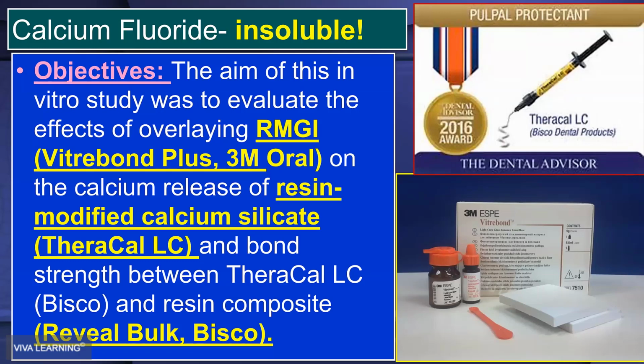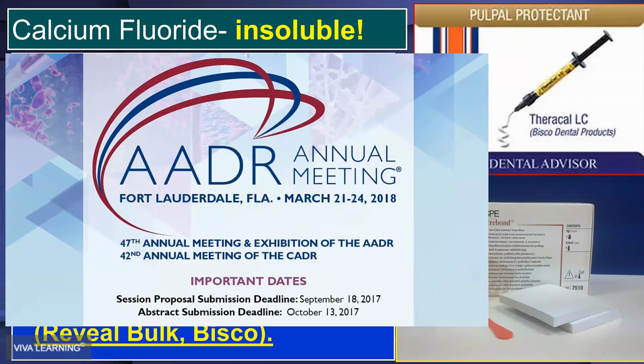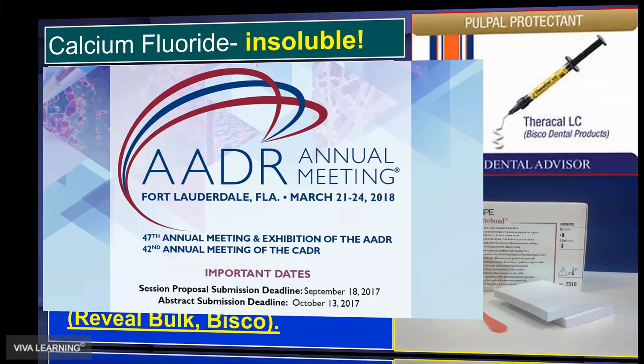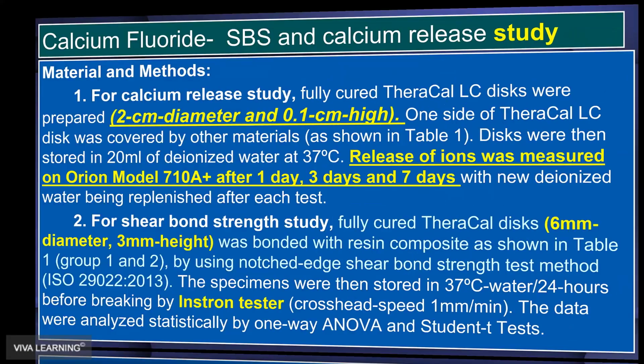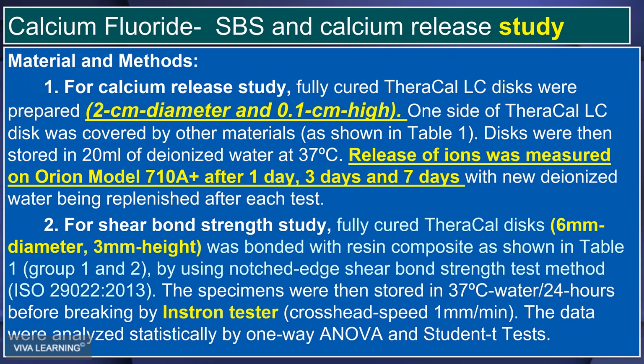Wanted to see how much calcium you get out, what the strains are. And I presented this at the AADR meeting, the American Association for Dental Research. And so for the calcium release, we had these 20 millimeter by 1 millimeter samples to just measure the calcium coming out at 1 day, 3 days, and 7 days. And for shear bond strength, we have these other different size samples, 6 millimeters by 3 millimeters.